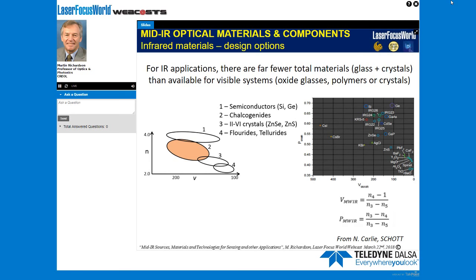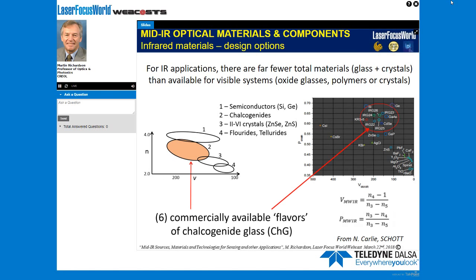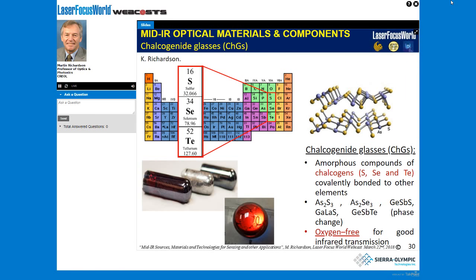The chalcogenides occupy a sort of unique space here, illustrated on both these figures. In fact, if you look at this encircled region here, this is the region of chalcogenides where there are a number of different chalcogenides, and we can hopefully use mixtures of chalcogenides to design optical glass materials for specific applications. I've just briefly summarized that chalcogenides really are this group here from oxygen to tellurium, but actually there are only really three chalcogenide materials that are used in optical materials: sulfur, selenium, and tellurium.